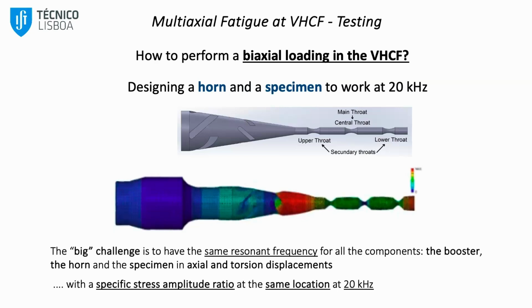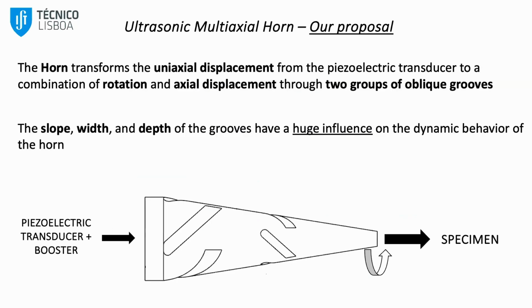The big challenge is to have the whole set working at the same resonance frequency, and another issue is that it should have a specific stress amplitude ratio at the same location. So we need to specify where we want to reach a certain stress, and we should combine the axial component with the torsional one at 20 kilohertz. So our proposal is to use a horn that transforms the uniaxial displacement received from the piezoelectric transducer and the booster, and it goes through the horn to the specimen, and at this tip will create a rotation movement and an axial movement.